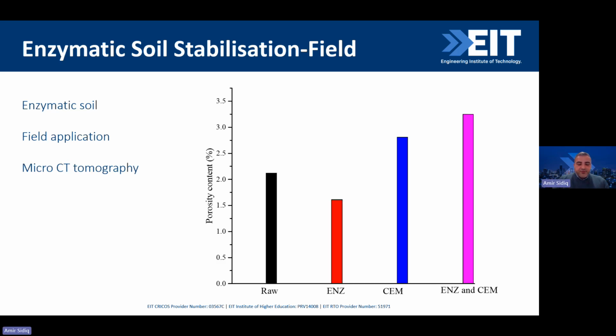The microstructure, using the porosity content only. Again, for the pores, for the raw material, the porosity is high compared to the enzyme. The enzyme actually has reduced it. Cement has increased the porosity again, and with the cement and enzyme, the porosity is also increasing. Now, the difference between the enzyme and cement, the porosity is actually increasing significantly, that particular residual. But comparing the enzyme cement with the cement only, it's not much. So here it's not much of the enzyme effect that's actually increasing the porosity, but actually the impact of the cement that is actually increasing the porosity.